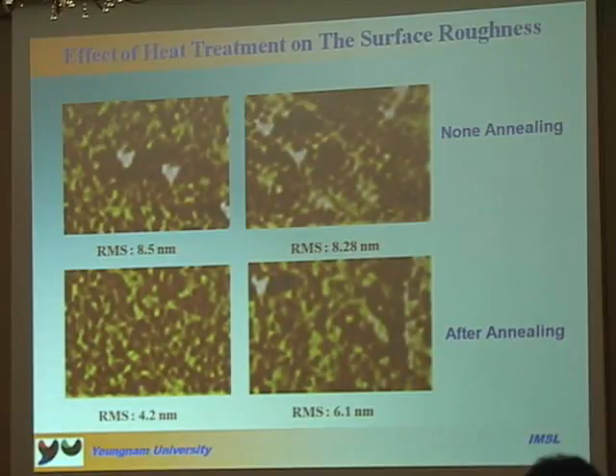After we have a very standard solution, a commercial solution, we try to investigate the effect of heat treatment on the surface roughness. In this study, we anneal the sample after spin coating the composite film. We investigated by AFM. You can see in the figure, after annealing we have lower surface roughness, very low, compared to the non-annealed case.